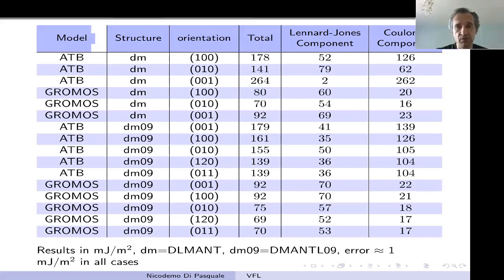But what we already observe here is that ATB is all atom and Gromos is united atom, the two structures, DM and DM09, and different orientations. So we have the Lennard-Jones component, and you can see here that the results for the Lennard-Jones component are quite close to the dispersive component in IGC. And then the main challenge that we had before: you can see for all atom models, we have very large Coulombic interactions, which was rather unexpected.